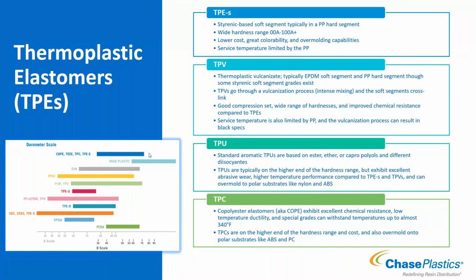The other thing to note about the vulcanization process is it will utilize a catalyst. A standard catalyst, if it's a phenol type, will result in some small black specks in a natural TPV - that's a normal occurrence. All the suppliers try to limit how much it happens, but it's normal out of TPVs. They do have special grades of TPVs that utilize a different catalyst so you don't have that problem, but just note, if you're getting a standard grade of TPV and it's natural with a little black speck here or there, that's normal - that's going to happen.